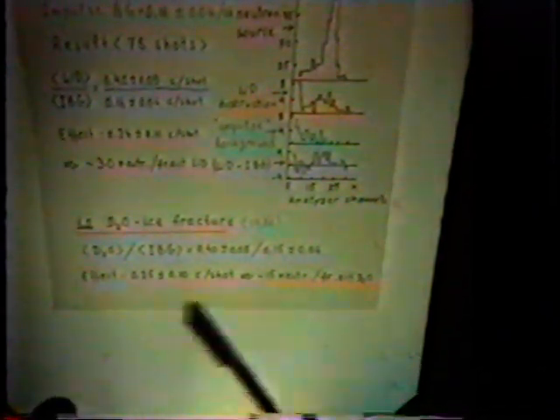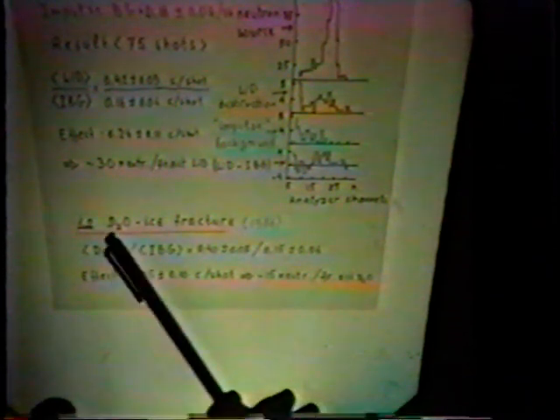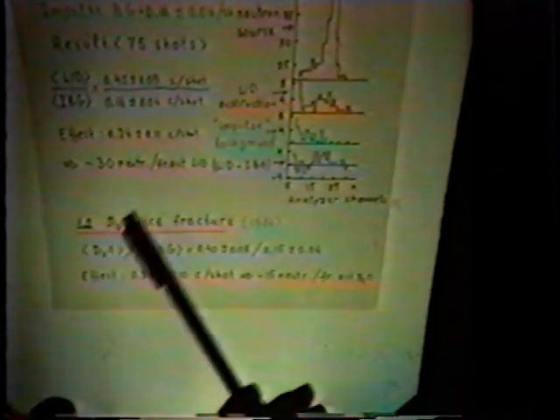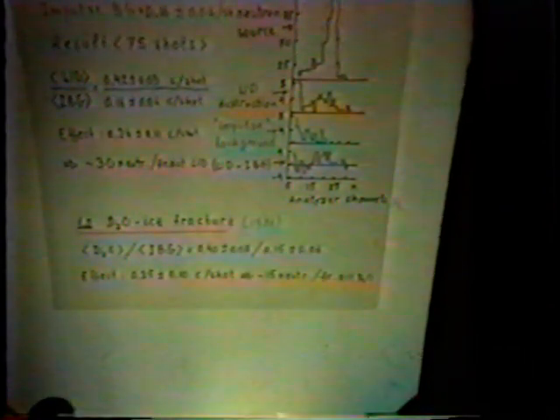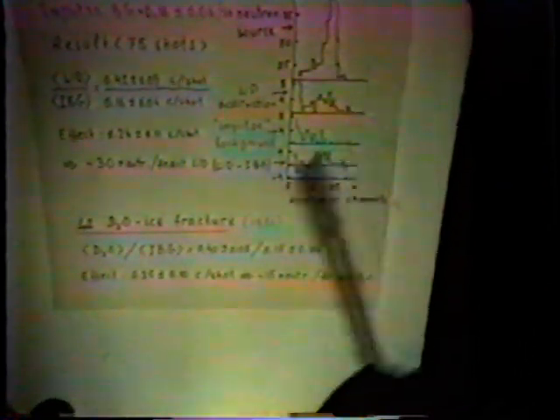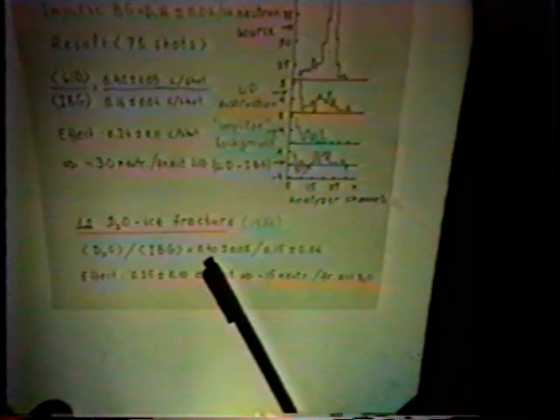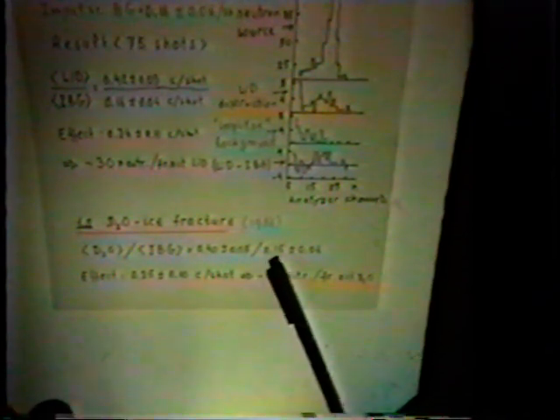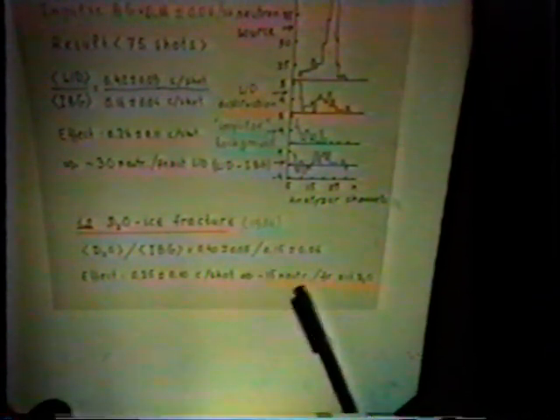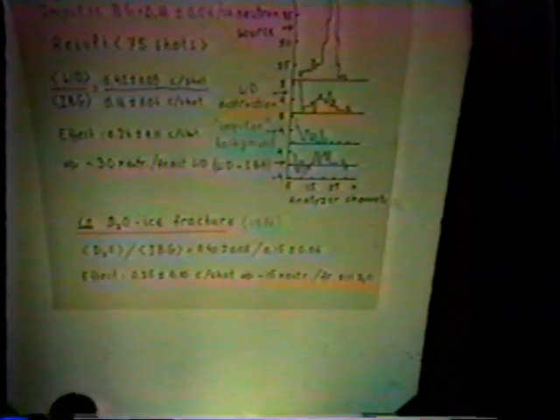In the same way, this group performed another experiment, this time with heavy ice crystals instead of lithium deuteride crystals, and the results are very close. The signal was 0.4, the background was about 0.15, and so it corresponds to about 15 neutrons per fracture act of a heavy ice crystal.